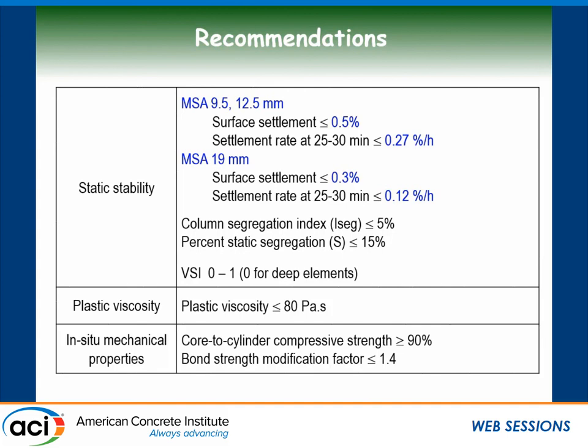Now, for these SCC mixtures, in order to prevent this very, very viscous concrete that prevents good bond, you should limit your plastic viscosity to 80 Pascal second. And we can translate that also to a V-funnel test and a T50 test. And if you do that, your in-situ compressive strength should be larger than 90% of your cylinders, and your top bar effect should be less than 1.4.